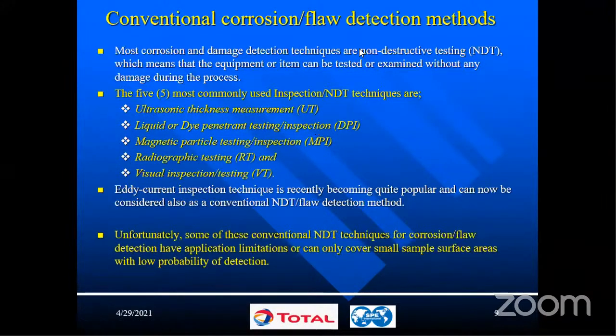So let me see, something is on my screen. So the conventional techniques, the five most conventional NDT techniques are listed there. Most of them are well known. I will start with the ultrasonic thickness measurement. Just a quick rundown. It's an indirect measurement where you send ultrasonic signals using special probes through a material, metal. And the time it takes for the signal to come back to the receiver, that time is calculated with the velocity to give the distance, which will now be the thickness of the material. So you measure the time the signal takes to come back and translate that to the thickness.